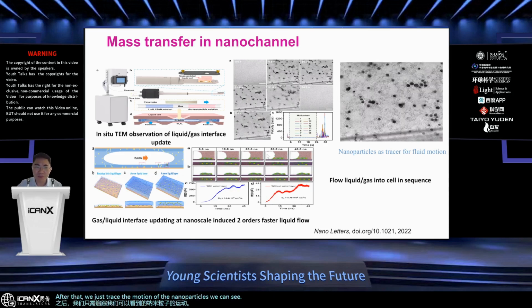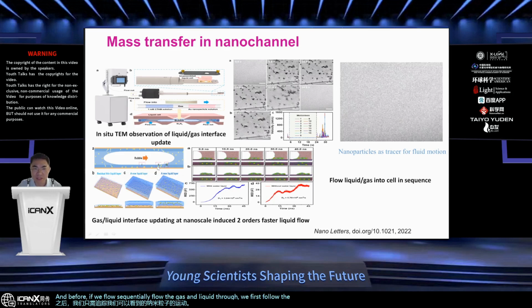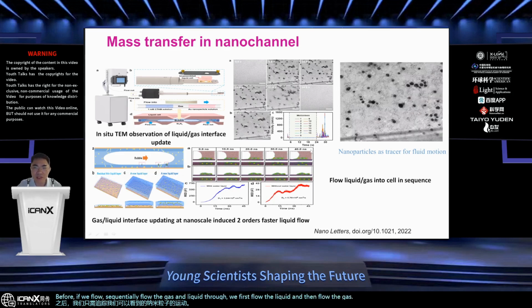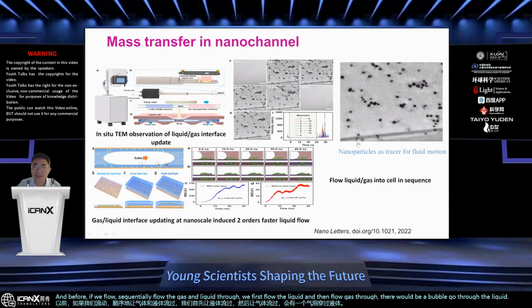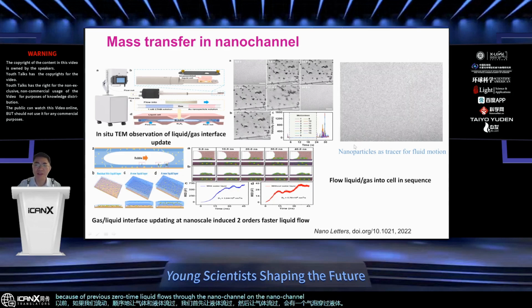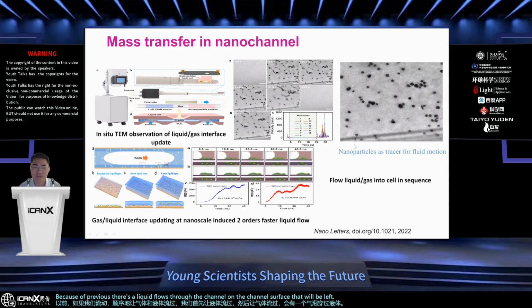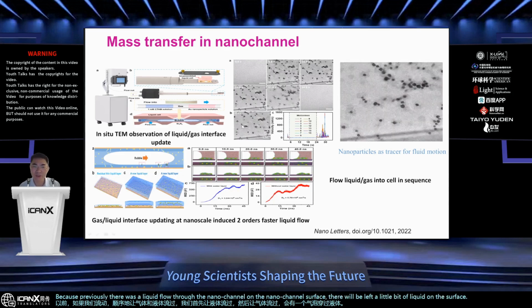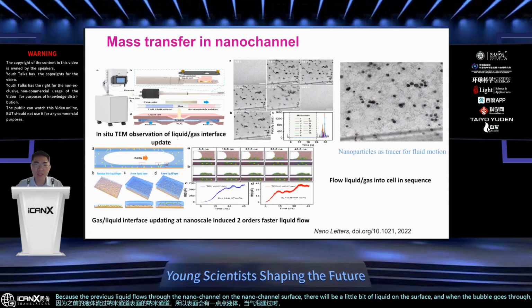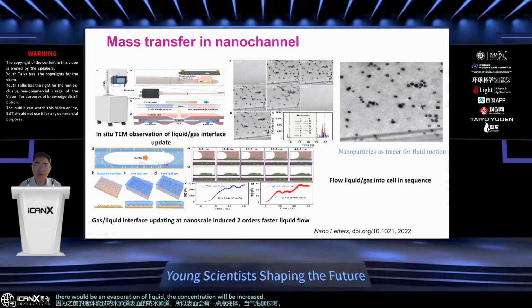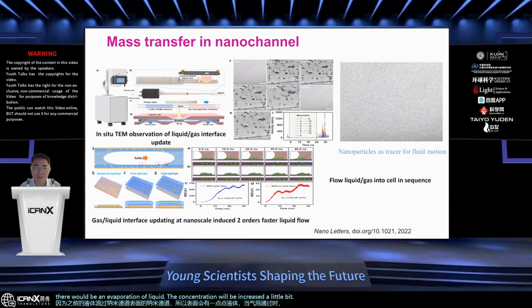We can see that if we sequentially flow liquid first and then gas through, there would be a bubble going through the liquid. Because previously the liquid flowed through the nanochannel, a little bit of liquid is left on the surface. And when the bubble goes through, there would be an evaporation of liquid.